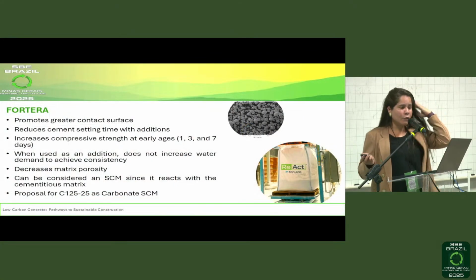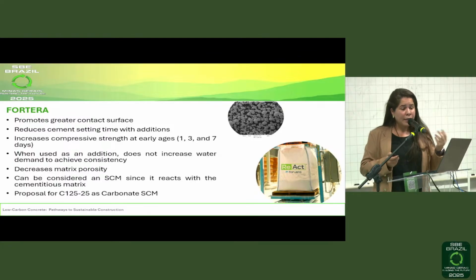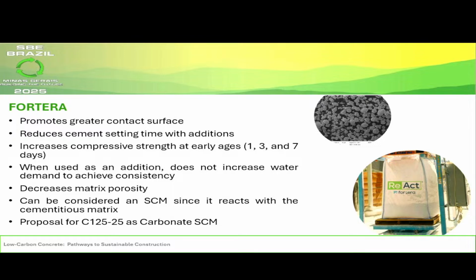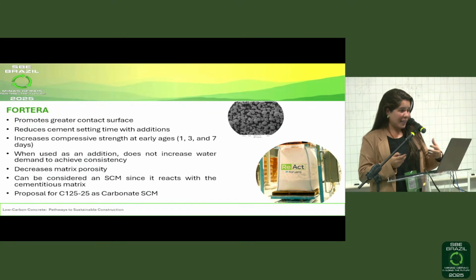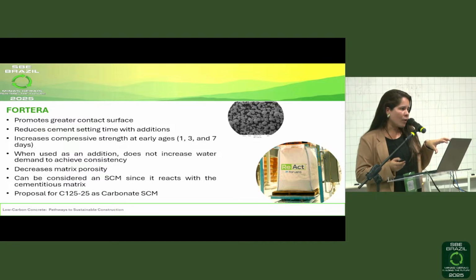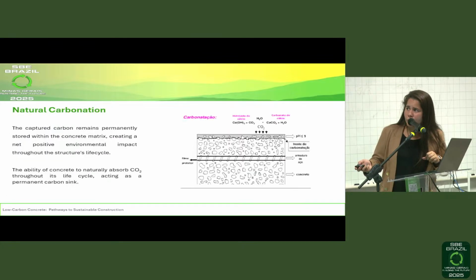There is also Fortera. Fortera is a company that I visited in San Jose in California, and they treat fill limestone with CO2, and they transform this material from inert to reactive, and it becomes an addition to cement. And it is being studied in one of the norms in the United States, C125-25, to become an SCM. Why? Because it has reactivity. So this material is being studied. It's a patent that treats this fill limestone. It is a widely available material treated with CO2, and it transforms the mineralogy of the material.